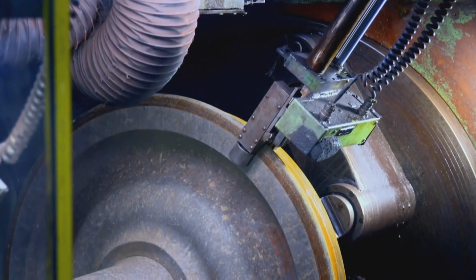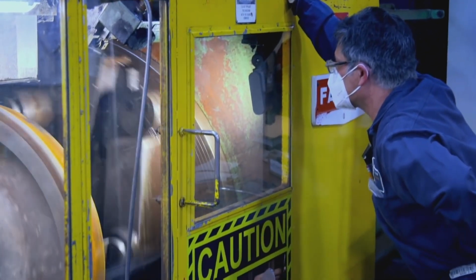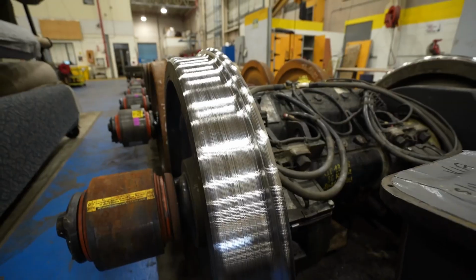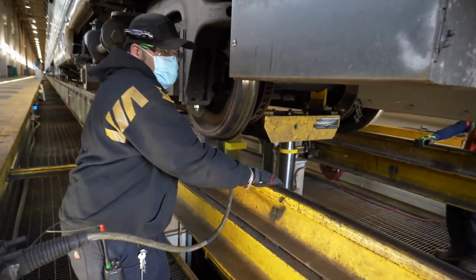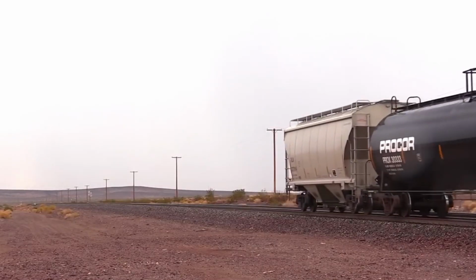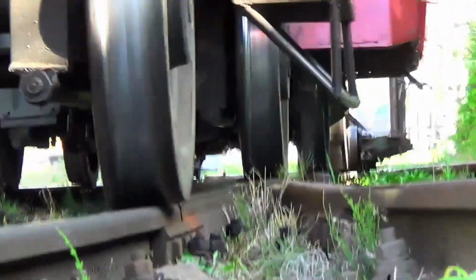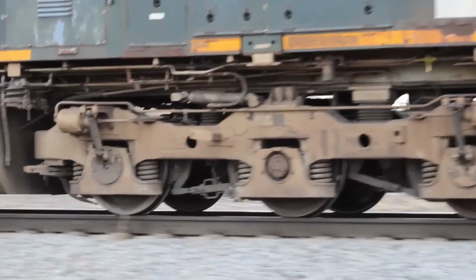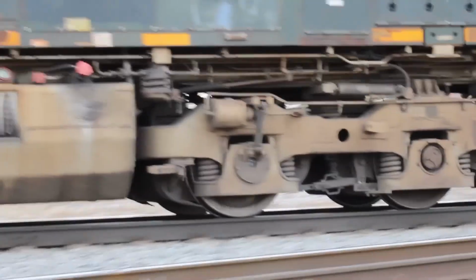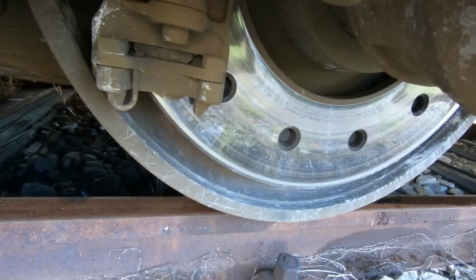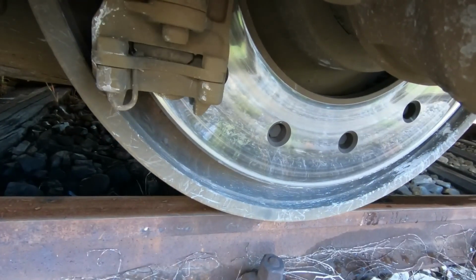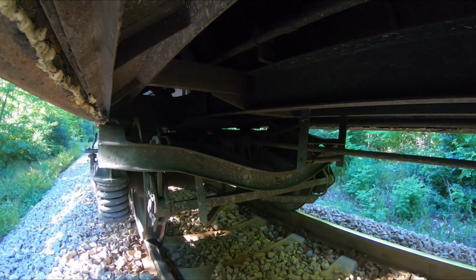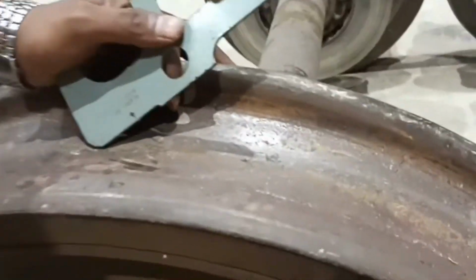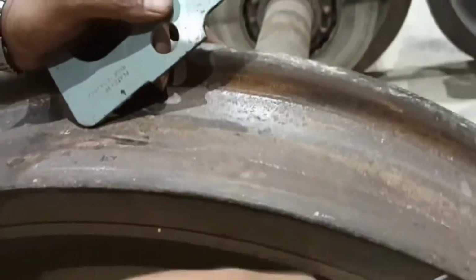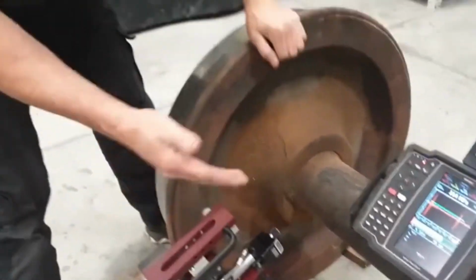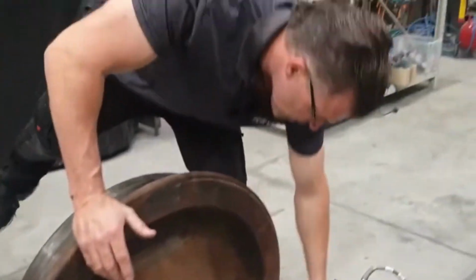Steel under repeated cyclic loading develops microscopic cracks at points of stress concentration. These cracks grow incrementally with each load cycle. Each revolution of the wheel under load, each thermal expansion and contraction, each imperfection in the rail surface that sends a shock through the steel. The cracks propagate from the inside out, parallel to the tread surface at first, then turning perpendicular and extending toward the outer surface. The wheel looks normal on the outside. It sounds normal. It measures within tolerance on standard inspection equipment, and then it does not.